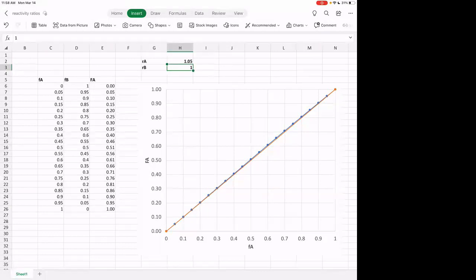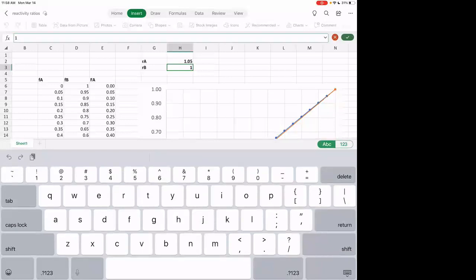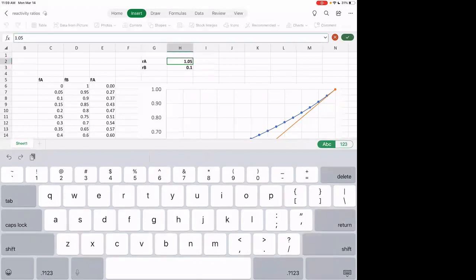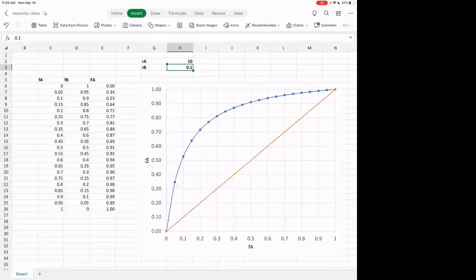Okay, and the one that we didn't talk about was called ideal copolymerization. You want to remember what that is. And what's the definition of an ideal copolymerization? The product of the reactivity ratios is 1. So if we make that 0.1 and make this 10, why is this an ideal copolymerization? It goes back to the definition of the reactivity ratios, that they're inverses of each other. And so remember what that nomenclature is for ideal copolymerization. It's in your notes. You can refresh your memory on that. So there's some special cases about these reactivity ratios that you really want to know and be able to recall.